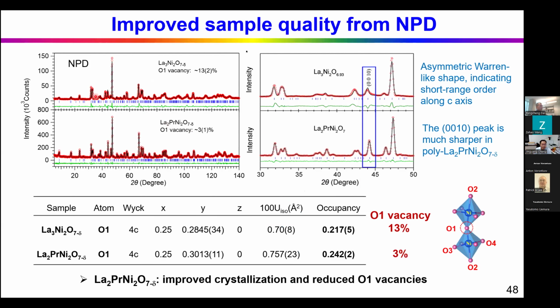So we measured the neutron diffraction at Oak Ridge National Laboratory. For these two samples, we found that for the undoped sample, especially for this 0010 reflection, the peak is quite broad. It shows a asymmetric Warren-like shape, indicating that there's some shorter range order along the c-axis. But in contrast, for the doped sample, it shows a very sharp transition. So this indicates that it has a much better sample quality.